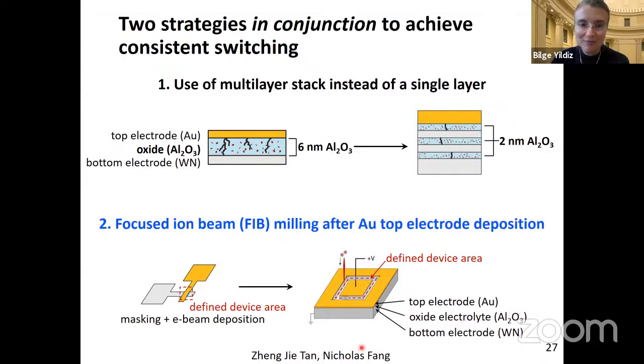And the peculiar observation that Professor Fang and his student had before they came to us to explore what's happening is the following: they're using an aluminum oxide as a resistive switching layer. And if they do two things, the switching becomes much more consistent. That is, dividing this relatively thick layer into even thinner layers, but that's not enough. On top of that, ion mill through the gold that is deposited as the contact on top of it. So focused ion beam milling to define the device area makes a big difference in the repeatability.